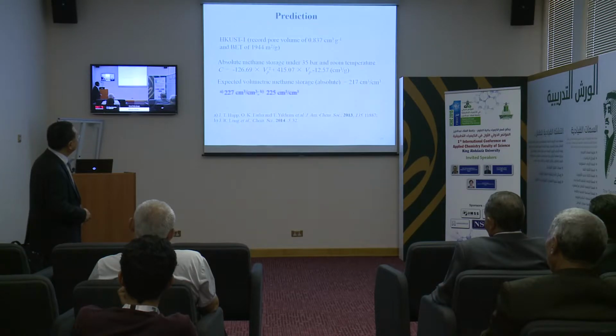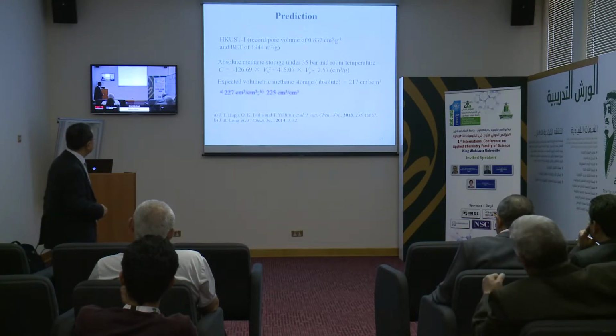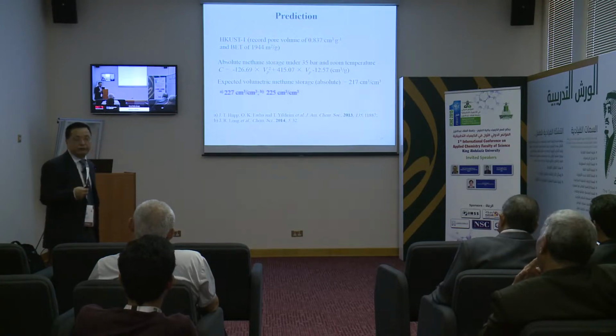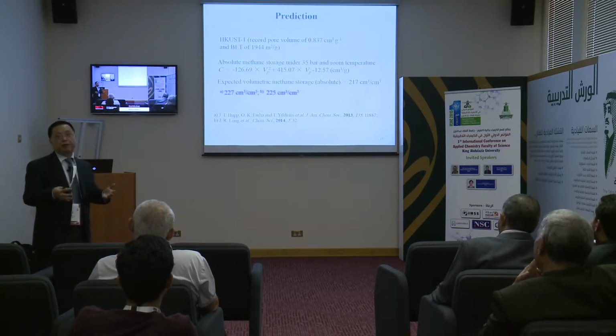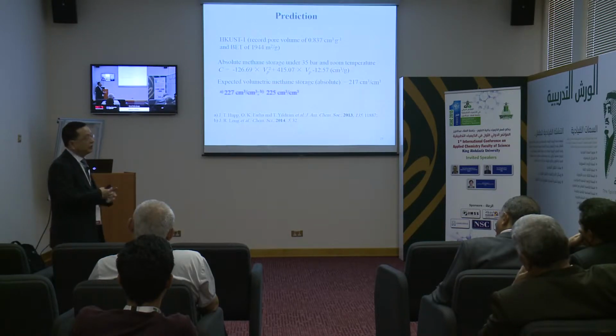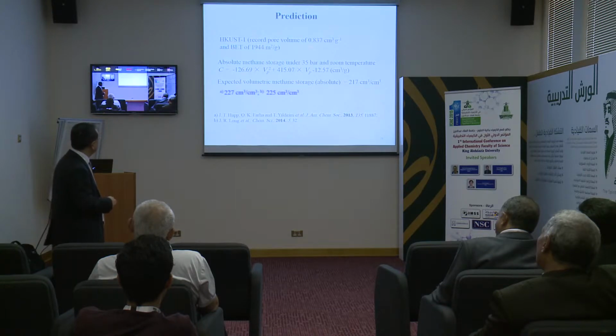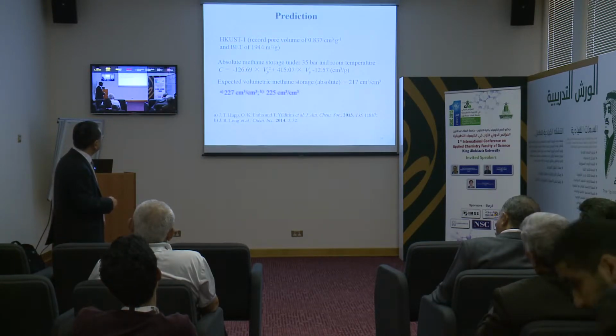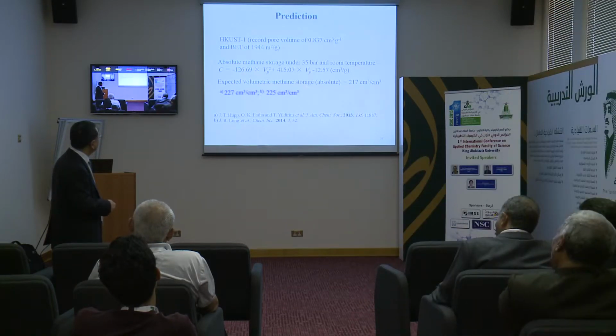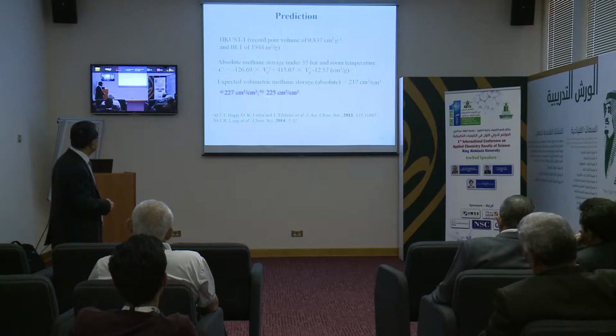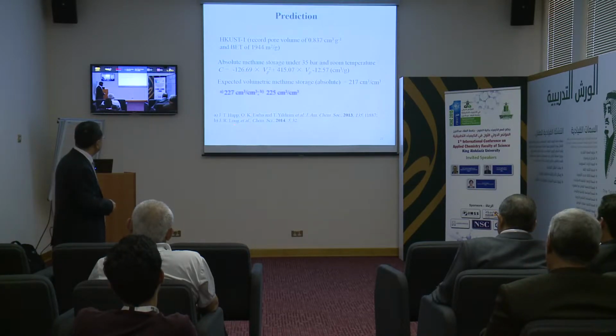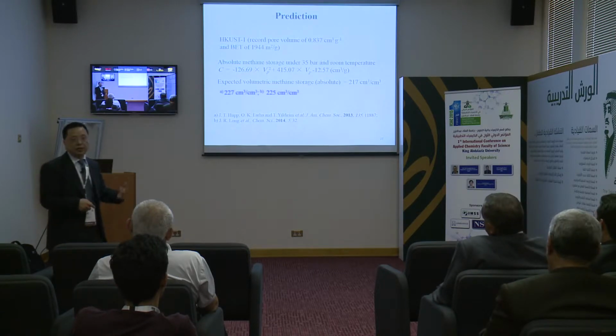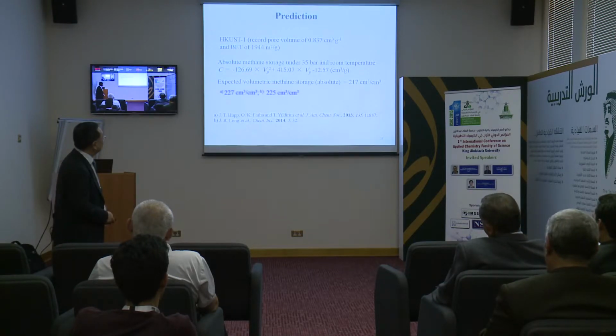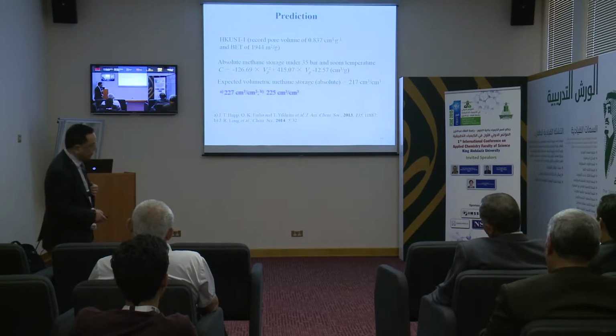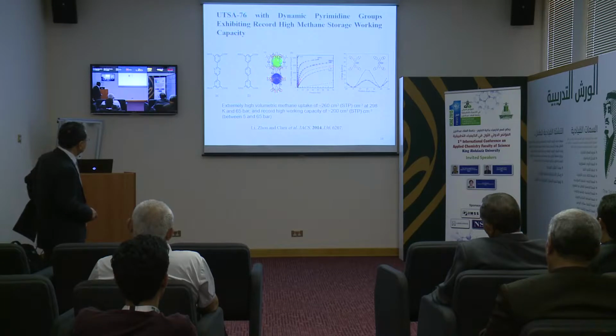And furthermore, we were even able to predict the literature data, because the HKUST-1 is one of the most famous, but different groups have reported different properties, mainly because activation is very sensitive, and we realize that this is the best one in terms of porosity. So based on this, from our empirical formula we expect this uptake amount, and it seems to match quite well with one of Omar's works and with another of Long's works. So it can help us to screen materials. And recently we also realized that it is an empirical formula under 35 bar. But it's still very challenging to increase the storage capacities.